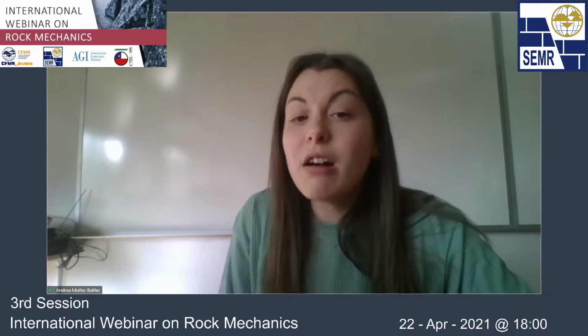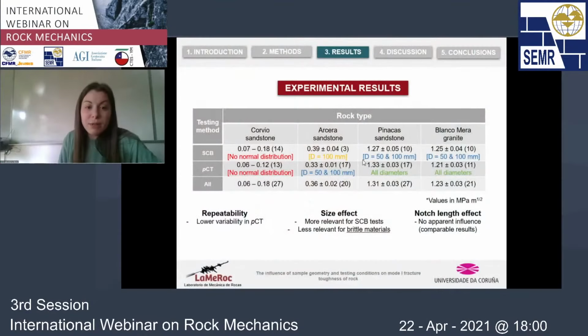So for the SCB, I would suggest using larger specimen sizes, because at least from this statistical analysis, what we observed was that for the weaker materials, we needed 100 millimeter samples to obtain values that conform to normal distributions. In the case of the PCT, it seems that the specimen size is not that relevant, at least for the harder materials. You're welcome.